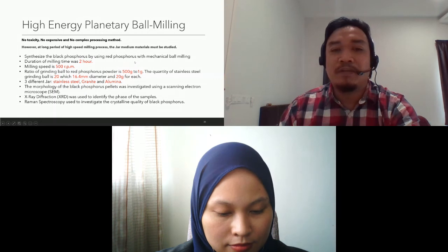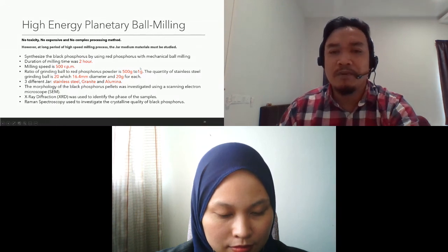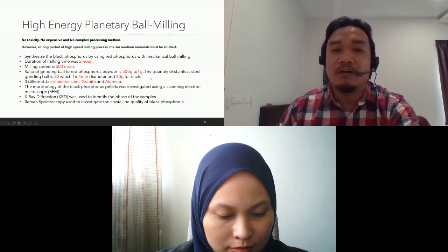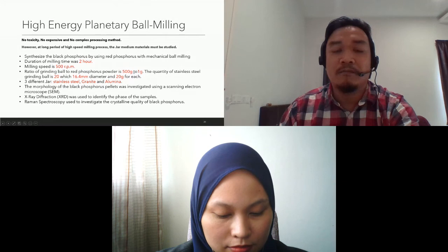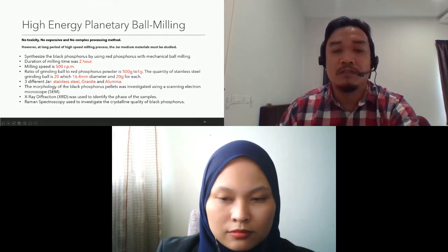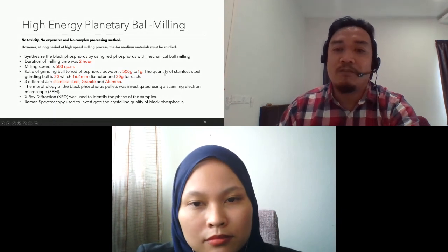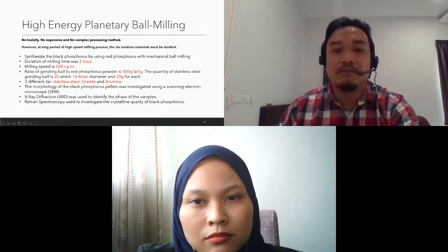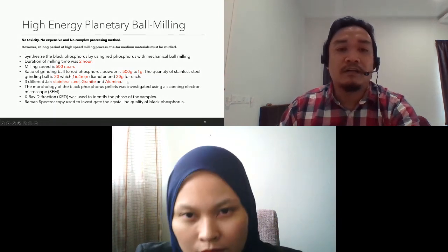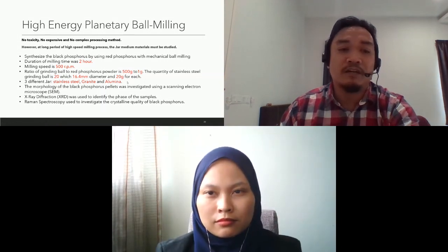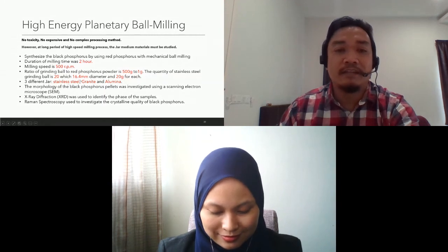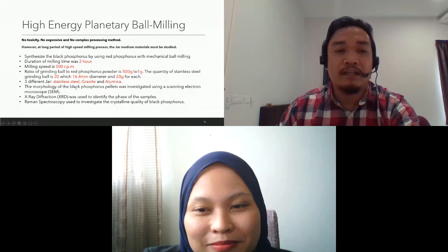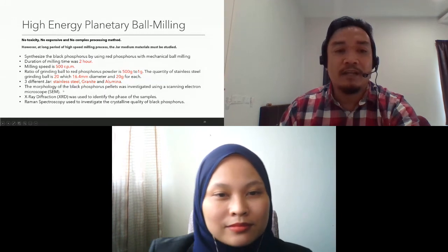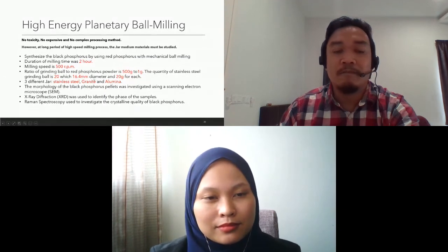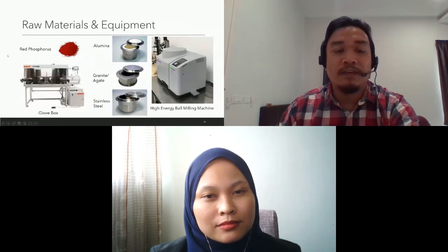The ratio of grinding ball to red P is 500 gram to 1 gram. Okay, this is quite small because if we want to produce 1 gram of BP, we need to use very many balls, this kind of weight of balls, 500 gram. The quantity of stainless steel grinding balls is 20, using this kind of diameter, and we will study the effect of 3 jars. The first one is stainless steel, the second is granite, and the third one is alumina. And finally, we will study the XRD, the Raman, and also the SEM of the synthesized powder. So we have here the RP.